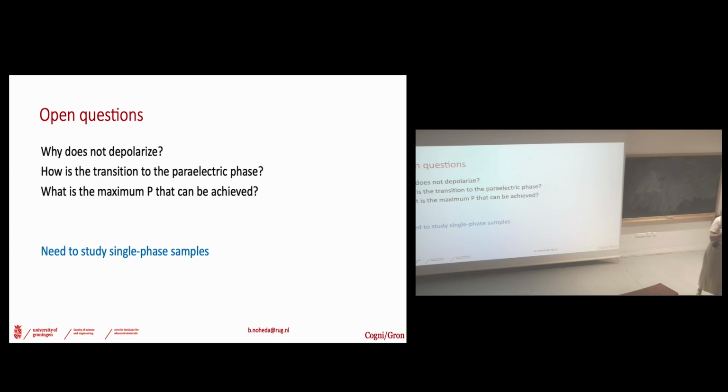So what you get at the end is a polycrystal, and it is actually very hard to get single phase that way, because you may still get a part of the tetragonal phase in the film, which is not polar. You may induce the monoclinic phase, which is the ground state. Part of the film may be monoclinic. It's also not polar. So when you get a specific value of polarization, it may be that the part that is polar in your film is just a small percentage of the total volume.